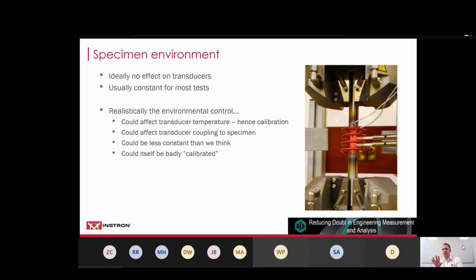However, whether it's constant or otherwise, the environmental control can affect your reading. So that specimen environment can impinge on your reading. It could be affecting the transducer temperature, like I said. It could affect the transducer coupling to the specimen. This one's one where we have to work hard, both we as manufacturers and operators, in terms of making careful test setup, getting good coupling to the specimen. That environment could be less constant than we think. Let's say we're doing this inside a temperature chamber or furnace, and we think we've got 500 degrees plus or minus 2. If things aren't right, then we could have plus or minus 5 degrees. Or we might have only 1 degree variation, but it's offset by 10 degrees. All of these things start to shift our test results. But I'll come back to that in a few minutes.